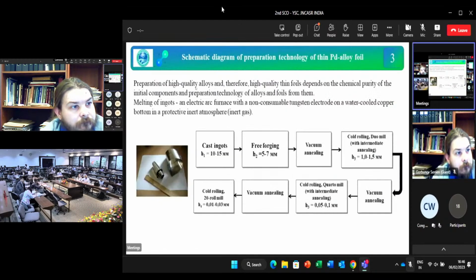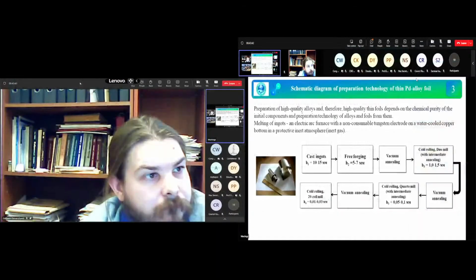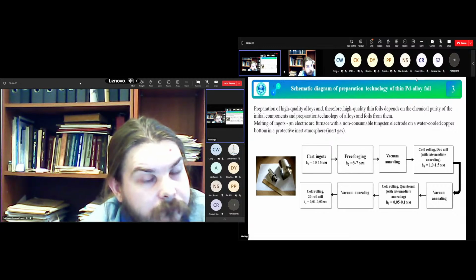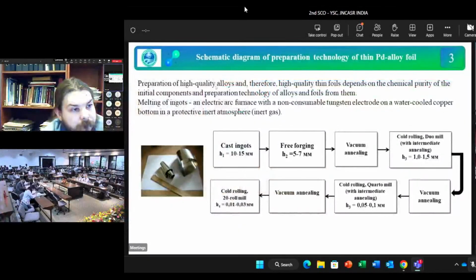A technology for the manufacturing of vacuum-type palladium alloy foils down to 30 microns in thickness has been developed. You can see the schematic diagrams of the preparation of such foils. It should be noted that the melting of an ingot is realized in a pure inert gas atmosphere using an electric arc furnace, a non-consumable tungsten electrode, and a water-cooled copper bottom. The rolling of ingots was realized with intermediate annealing in a vacuum furnace using 4-high and 20-high roll mills.